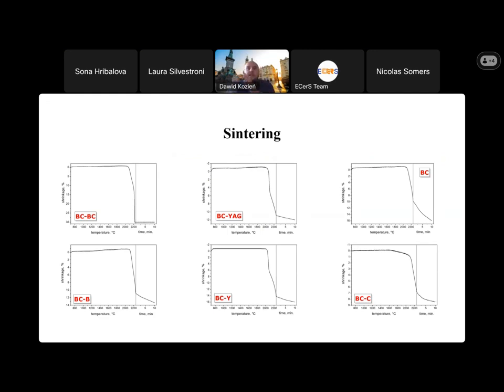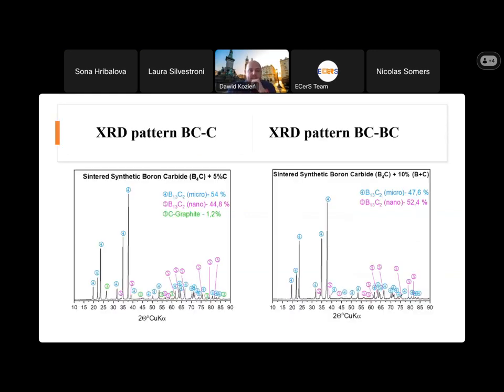Of course, we have different sintering temperatures. Some additives have the lowest temperature, while some raise the temperature of the synthesis. But what is important is that the carbon doesn't want to go into the structure of the boron carbide. It was very problematic, and the problem was that during the sintering we have a graphite structure, which is the weakness of the structure of the composites.